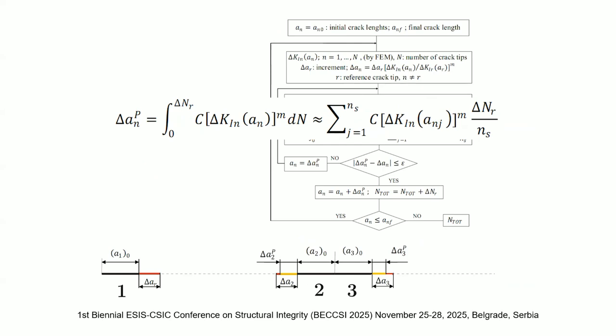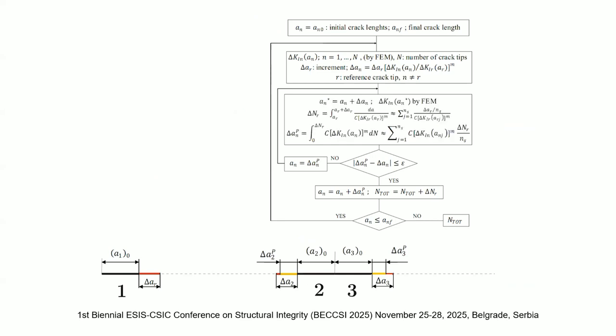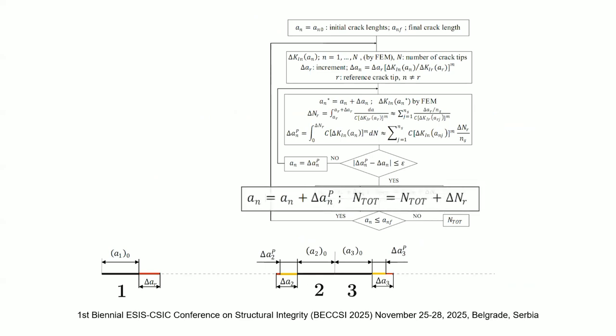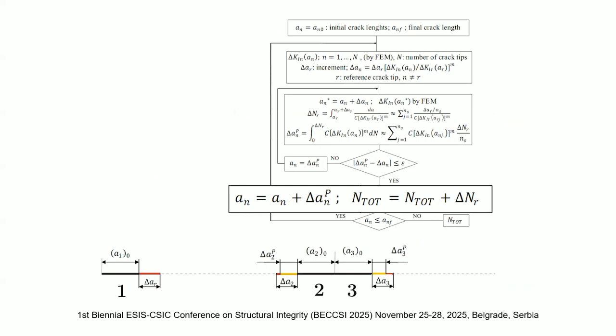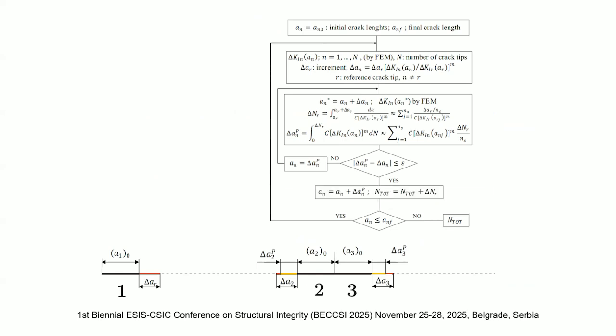We receive convergence when the difference between the assumed and calculated crack length is less than some limit which we give there, some tolerance. And then we repeat this. We repeat this until we reach some final crack length. This final crack length can be determined by when fracture will occur, if a crack reaches our critical crack length. So, some crack length before fracture occurs.